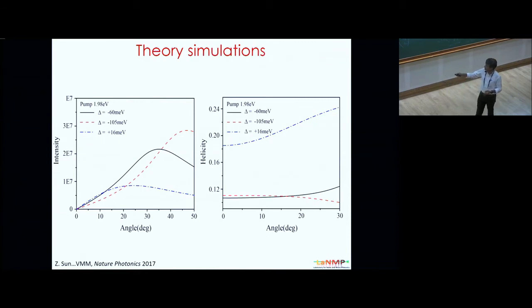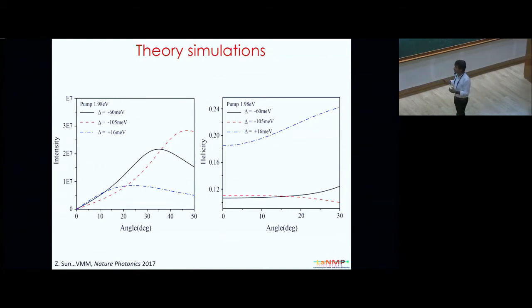However, the error bars that we're getting at the large angles do not really reproduce this. However, it seems like we have captured the basic physics, which is that the intervalley scattering and the exchange interaction that happens in these systems, as well as the TE-TM splitting that happens in the cavities, are responsible for why we are losing this helicity.